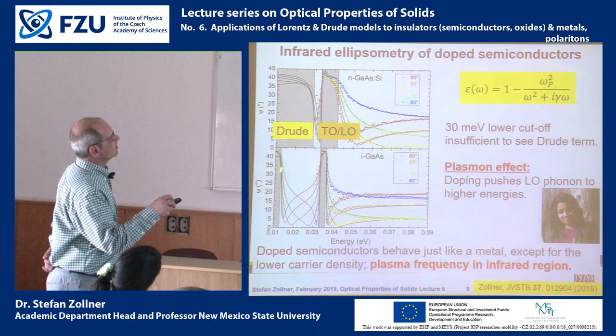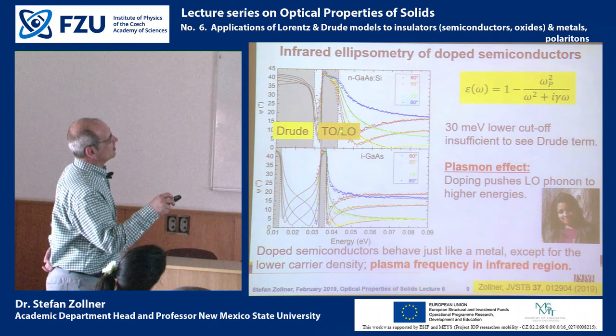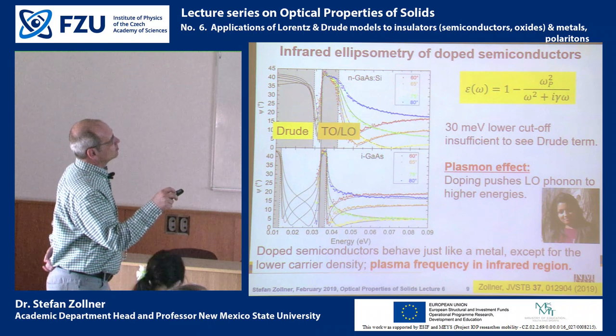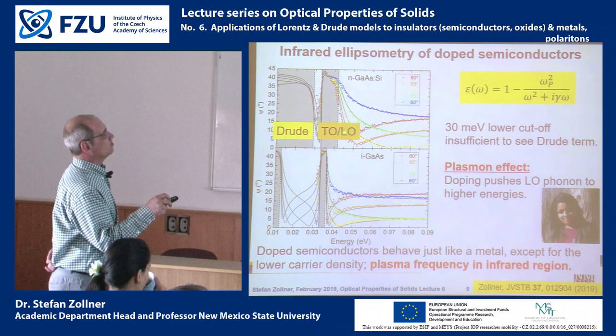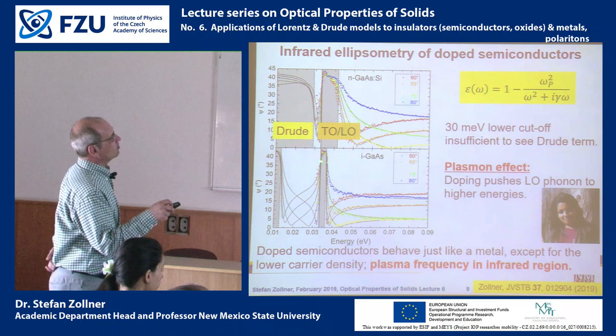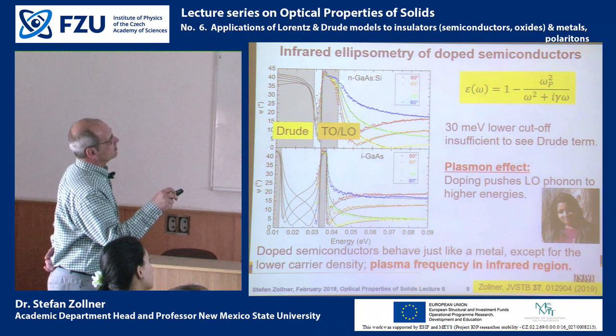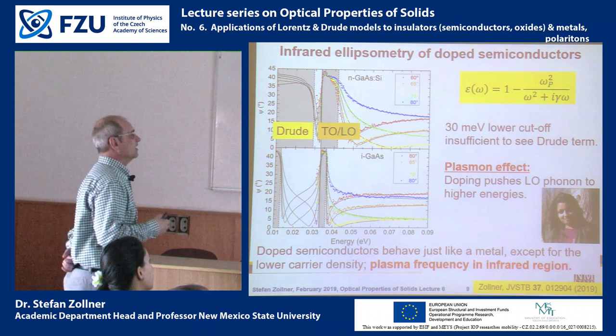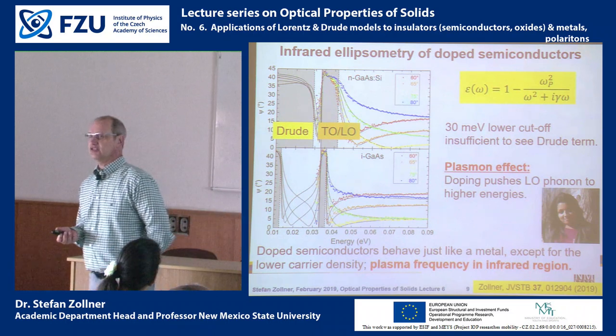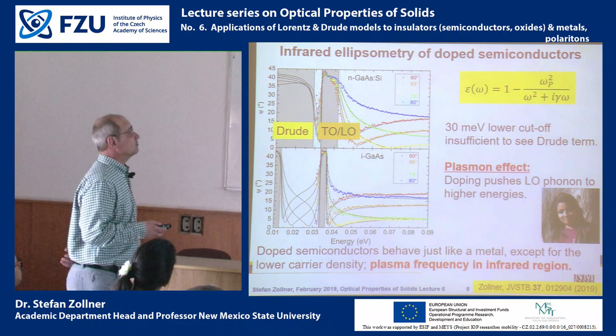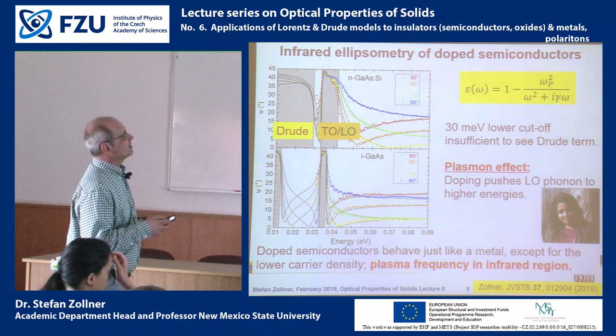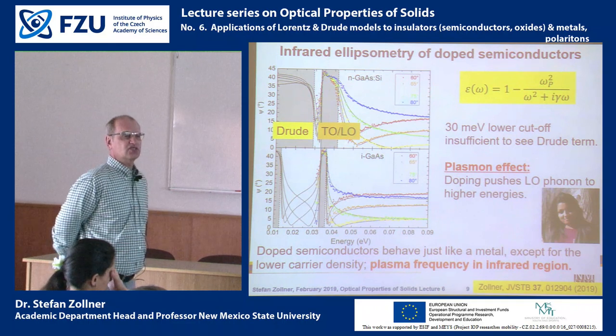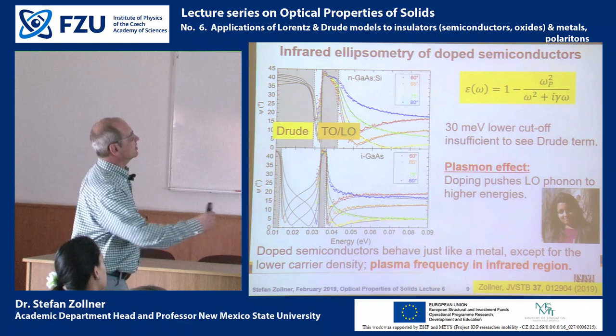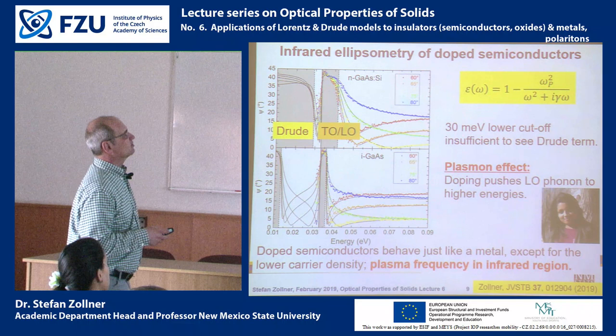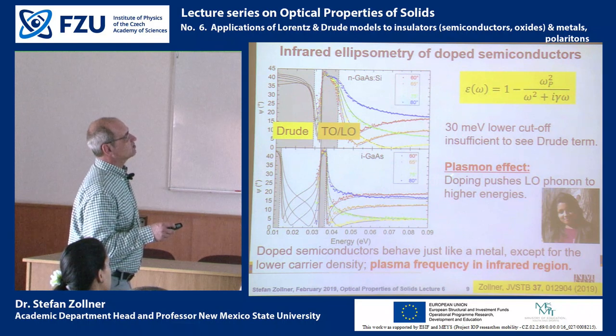But in addition to the width of that first band, what we also see is that the longitudinal optical frequency is pushed towards higher energies by the doping. So in the undoped case, the TO-LO Reststrahlen band is very narrow, but it is much wider in the doped case. And that comes from the fact that these free carrier oscillations are longitudinal oscillations, and therefore the free carrier oscillations can interact with longitudinal optical vibrations, and therefore the LO frequency gets pushed to higher energy. This is known as a plasmon, that the doping pushes the LO phonon to higher energies.